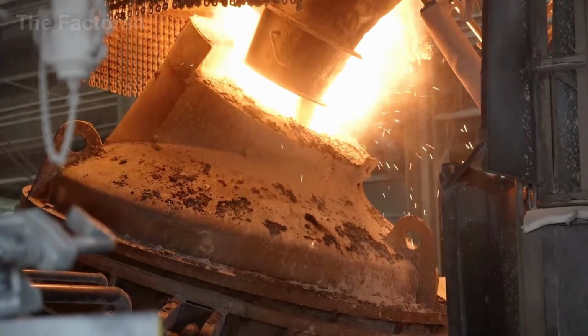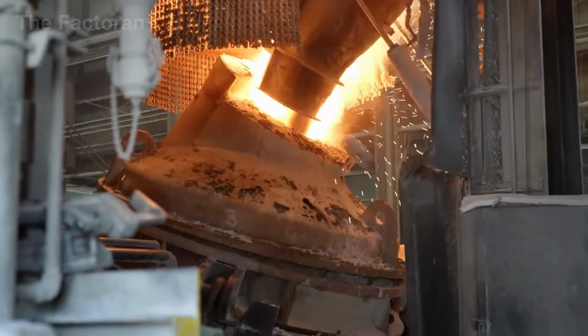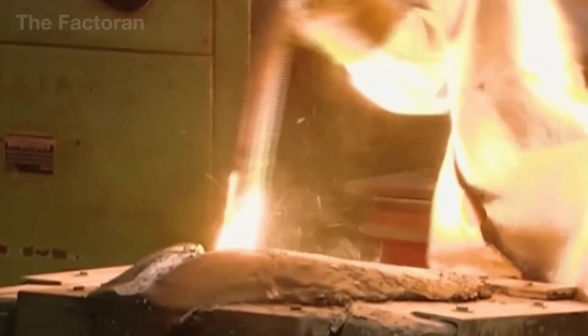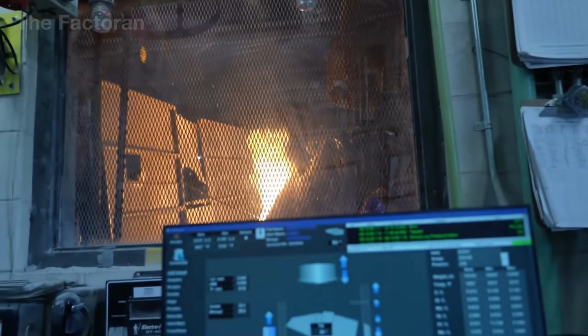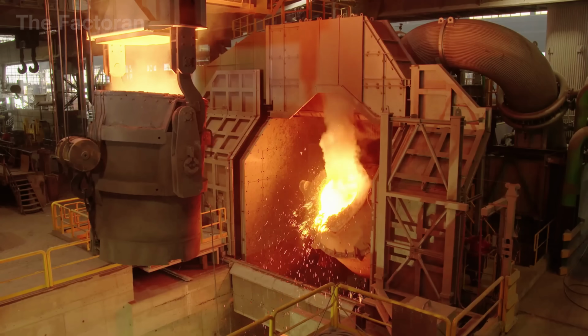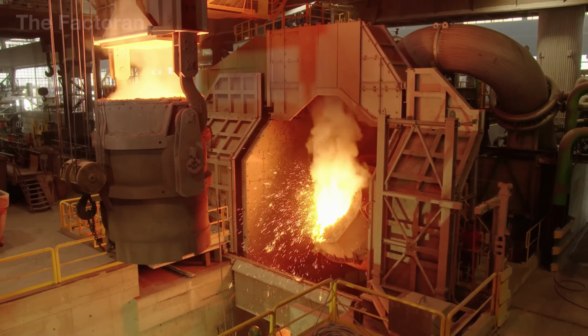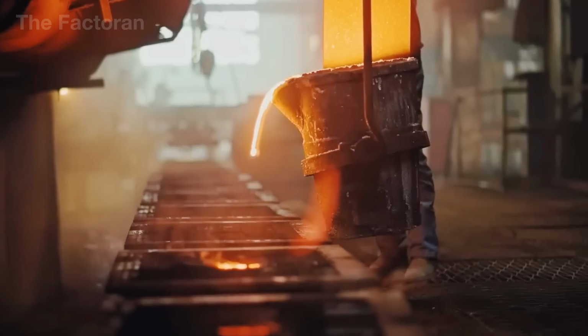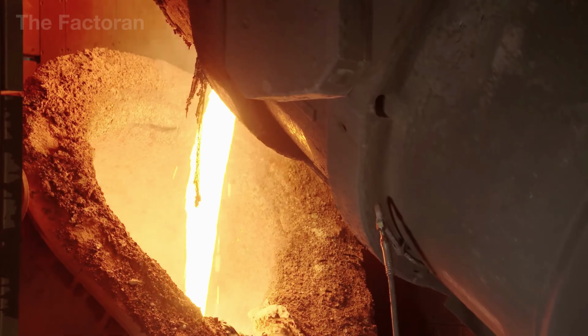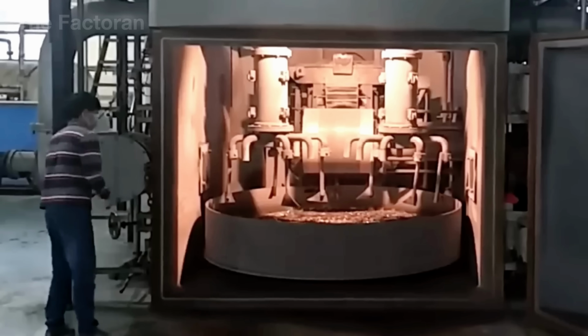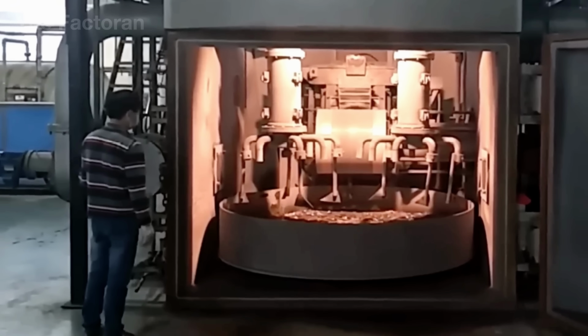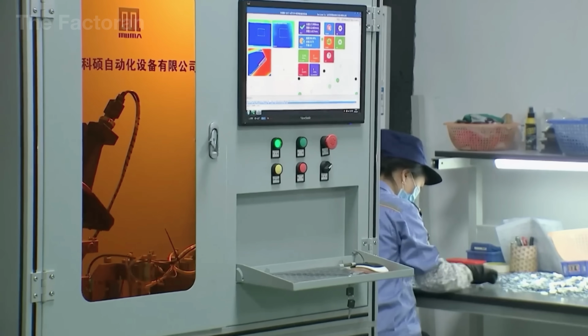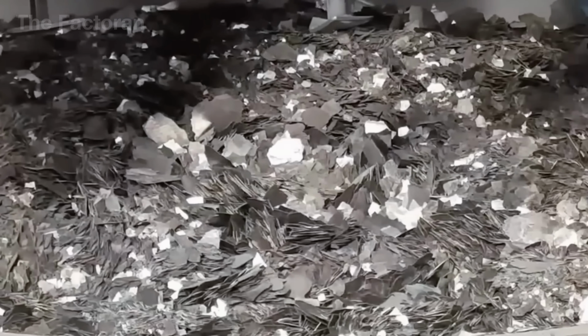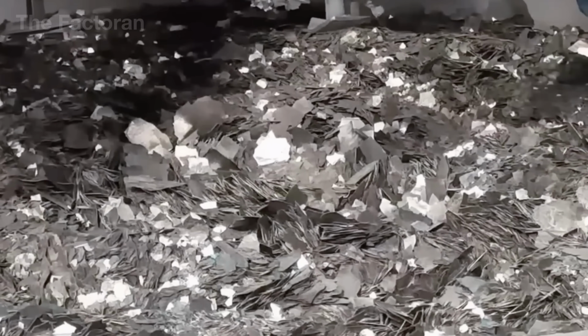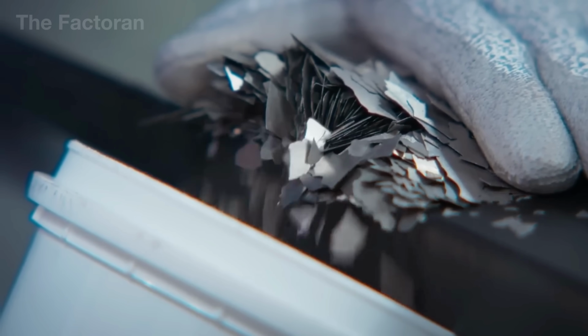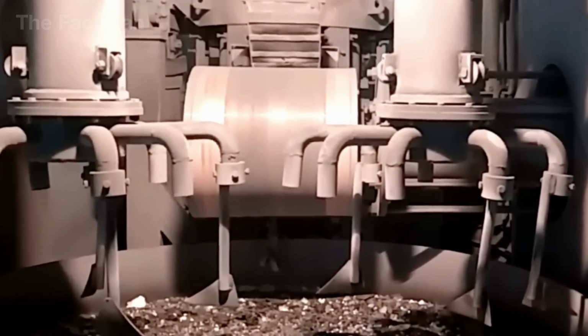The mixture is heated continuously for about 2 to 4 hours, allowing all metals to melt completely and blend into a uniform alloy. The heating duration is precisely calculated to achieve the ideal crystalline structure while preserving the integrity of the rare elements. For rare earth magnets, once the metals have fully melted, the molten alloy is rapidly cooled on a rotating drum within a few seconds. This technique of instantaneous cooling causes the liquid metal to solidify into thin metallic flakes with fine and uniform crystal structure.